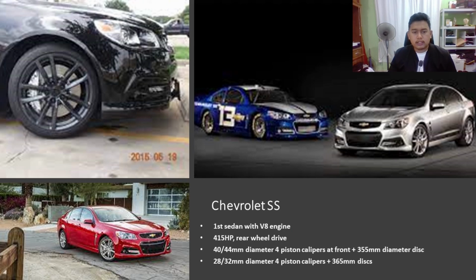The first model is the Chevrolet SS, the first sedan with a V8 engine, producing 415 horsepower with rear-wheel drive, and Brembo has produced oversized brakes in order to match the horsepower produced by the Chevrolet SS. For this car, 40 to 44 mm diameter 4-piston calipers are placed on the front to work in conjunction with 355 mm discs. On the other hand, at the rear wheels, 28 to 32 mm diameter 4-piston calipers are combined with large 365 mm discs.